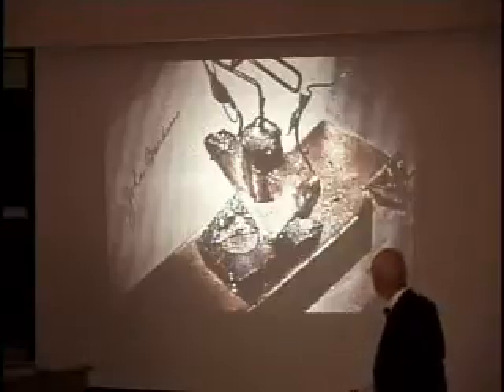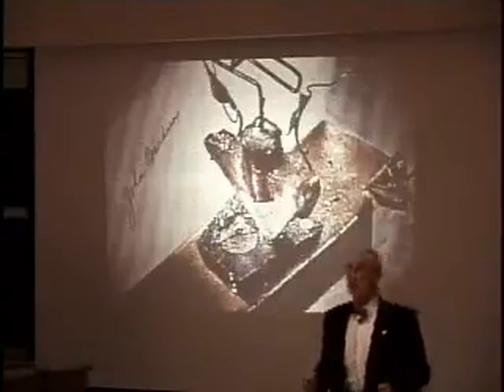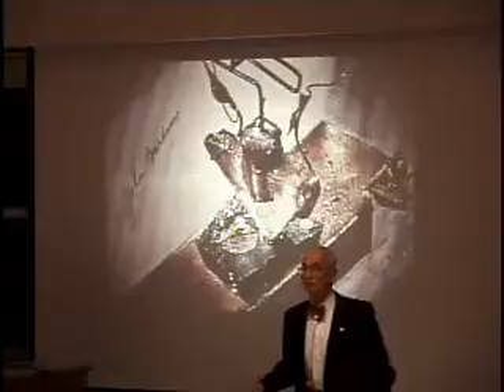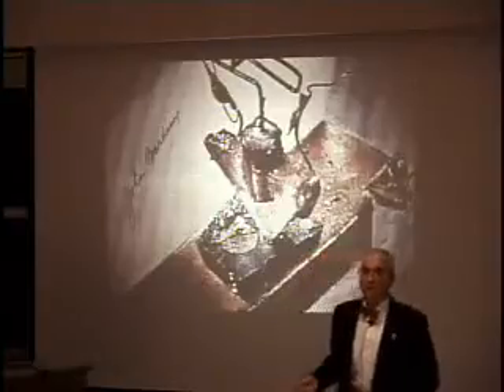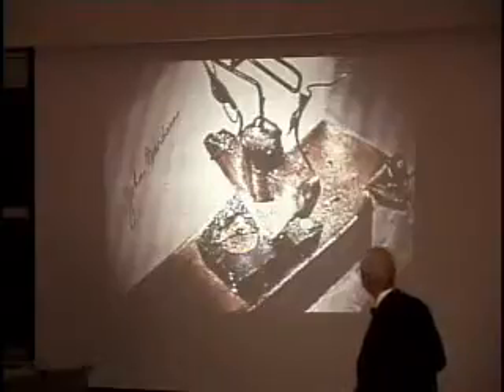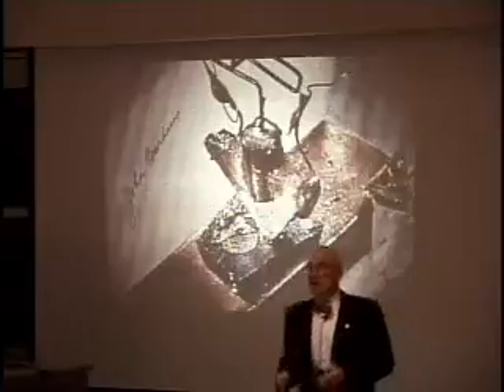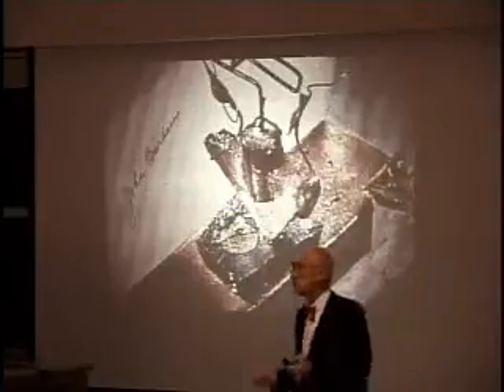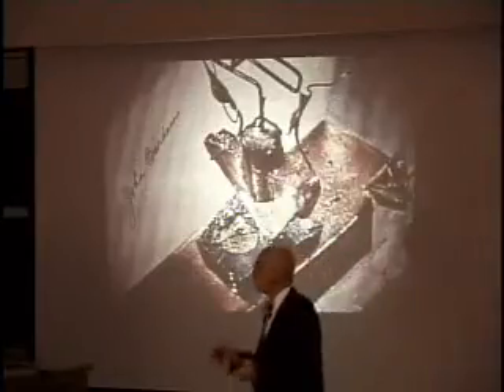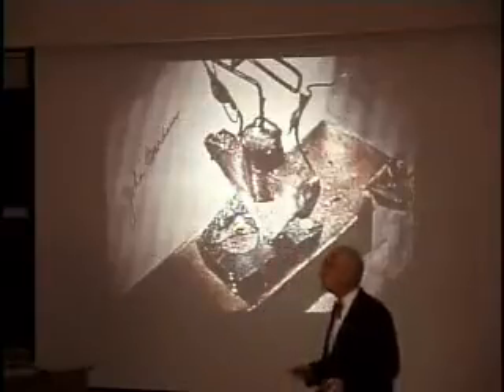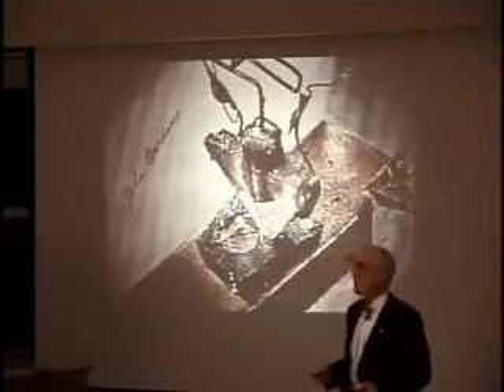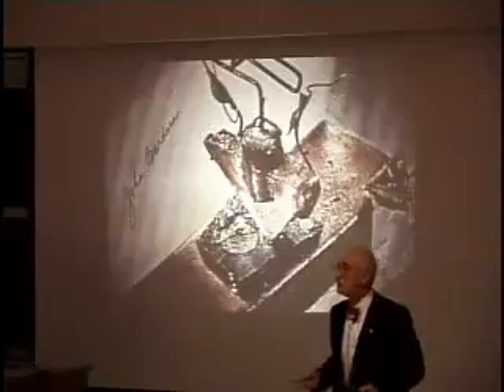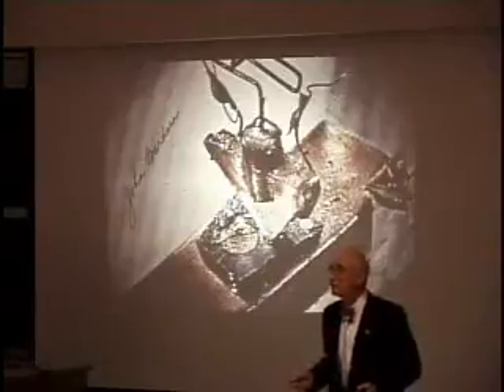You didn't have germanium to burn. You didn't reach in your pocket and get some more. You didn't go into the cabinet and find some more. There wasn't much. And they used the same piece of material over and over. But at any rate, Walter moved the point out to the edge. And it's typical when you do experiments like this, you change your bias. So the thing did not work as a field effect with the bias that it should have had. It worked as something else when they reversed the bias and they knew they had something else.